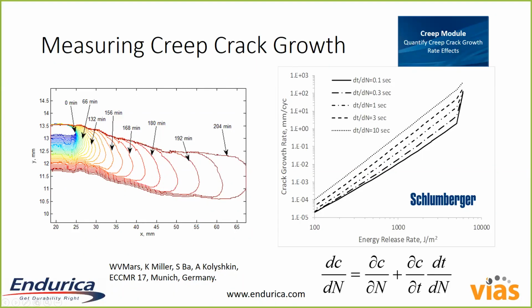The crack growth rate plot that I'm showing you on the upper right here is a set of computed, combined creep fatigue type curves, and you can see that the predicted curve actually depends on the period of the cycle. So if you have very rapid cycling, there's not enough time for much creep to happen, and so at a given energy release rate, you have lower crack growth rates. That's the solid line. Versus if you cycle on a much slower time scale, say 10 seconds, then the rate of crack growth per cycle actually goes way up because creep crack growth is part of this.